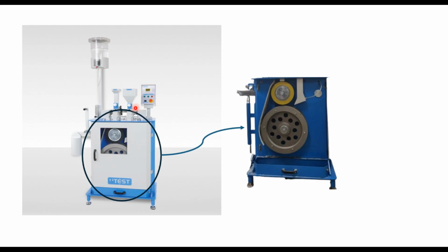Then you have an arrangement here to feed the silicon carbide or sand at the rate of 6 gram per minute, and also water at the rate of 50 to 75 milliliter per minute during the test. In the first part of the test, we feed this sand or silicon carbide grit plus water, and the second part of the test